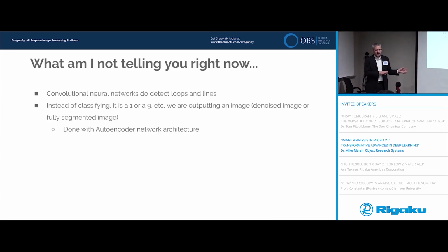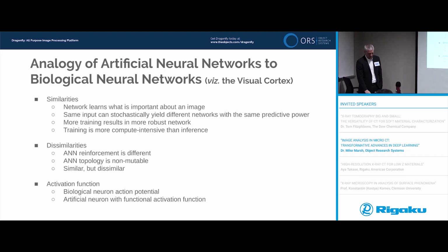Okay, in this case, we're mapping a labeling problem of, is this a 3 or is this a 4 or is this a 9? In our case, we're taking a square set of pixels that have grayscale values, and we're returning a square set of pixels that are segmented. This is my silicon carbide fiber. These pixels are my silicon carbide coating. These pixels are my pores. So instead of mapping 784 pixels to one score, I'm mapping 784 pixels to 784 pixels. But basically, the network topology can still be the same.